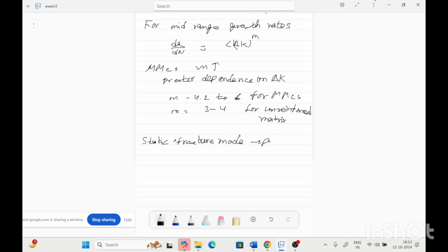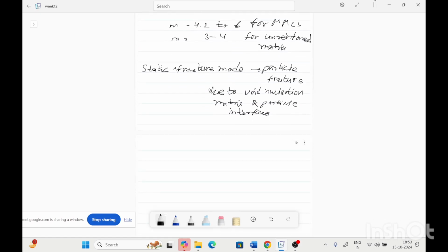That will lead to first particle fracture and due to void nucleation between the matrix and particle interface. So the particle fracture with the high growth rates means when the growth rates are high, crack growth rate is high, so particle will fail in the stage 2.